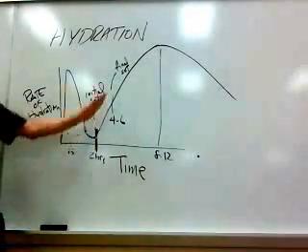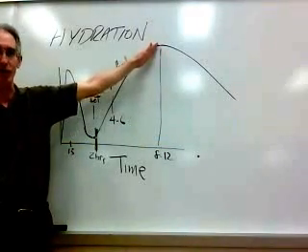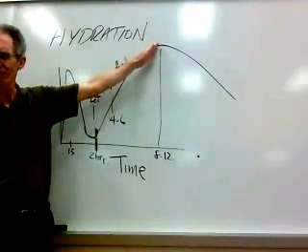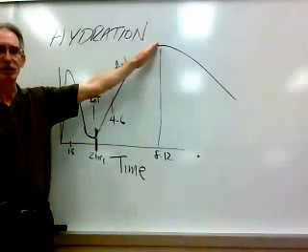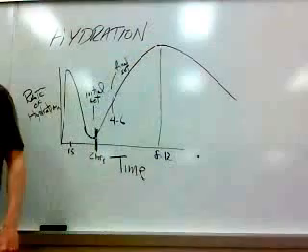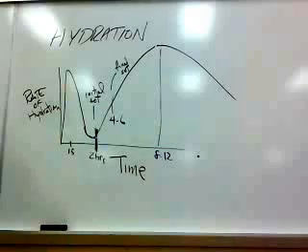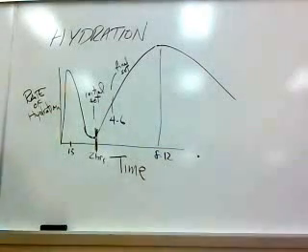Okay? The rate of hydration peaks out at 8, 12 hours, whatever, somewhere in there, simply because there's less unhydrated cement available. And also the water that's available is having a tougher time getting through all these crystals to hydrate cement. So that's why it starts to slow down.